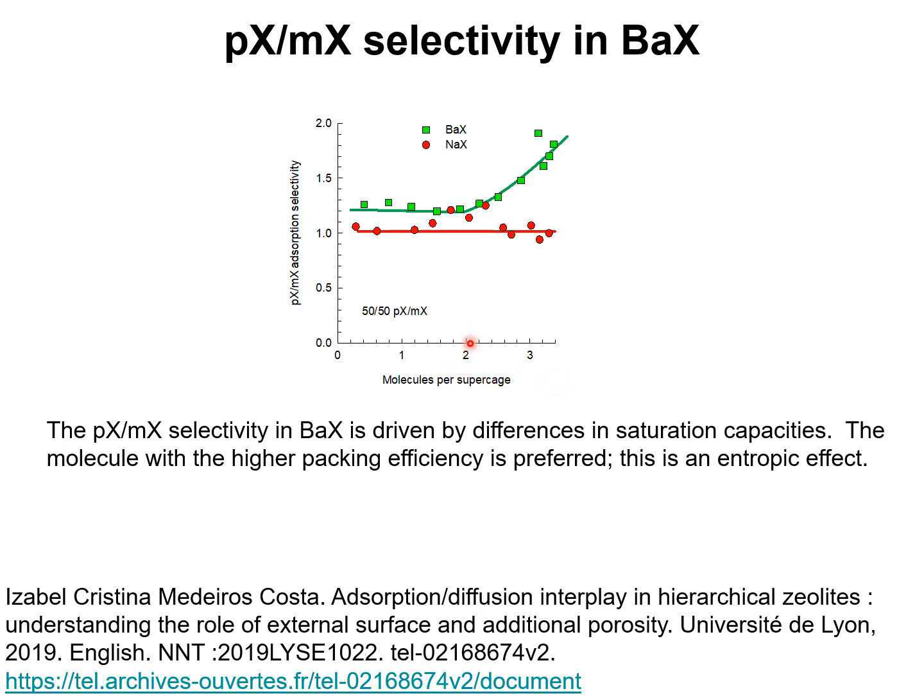We note that for BaX zeolite, the adsorption selectivity of para-xylene with respect to meta-xylene is just about unity or thereabouts till a loading of 2 molecules per supercage.